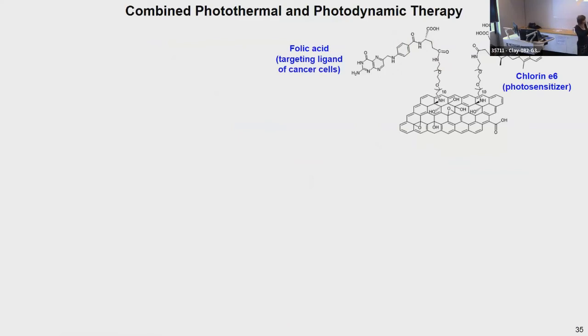In this case, we used the epoxide ring opening and we mixed the graphene oxide with two different amines. So we could conjugate folic acid, which is a targeting ligand of cancer cells because it can bind to the folate receptor, which is overexpressed on the surface of cancer cells. And we also conjugated chlorin e6, which is a photosensitizer, allowing us to generate reactive oxygen species under light irradiation. So this is what we did.